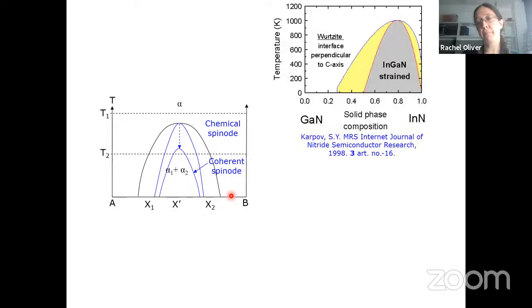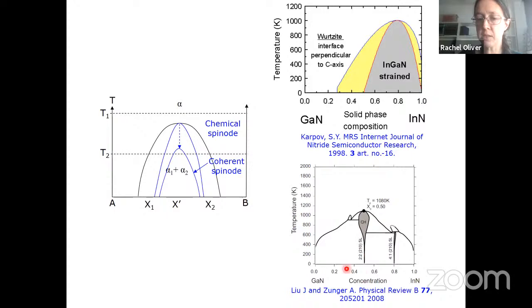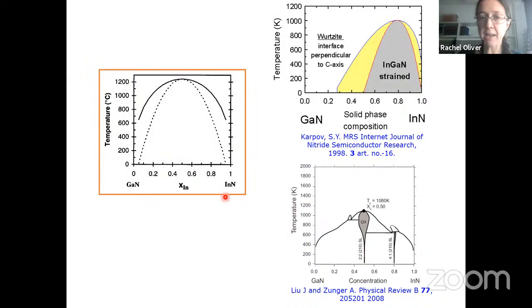Now, people started to take into account the impact of strain in their calculations of the phase diagram for indium gallium nitride. Here's a version from Karpov, and then later a much more sophisticated calculation by Liu and Zunger, but both attempting to take into account the impact of strain on this phase diagram that was originally calculated. And comparing to the original Ho and Stringfellow phase diagram, what we can see is that these things look very, very different.